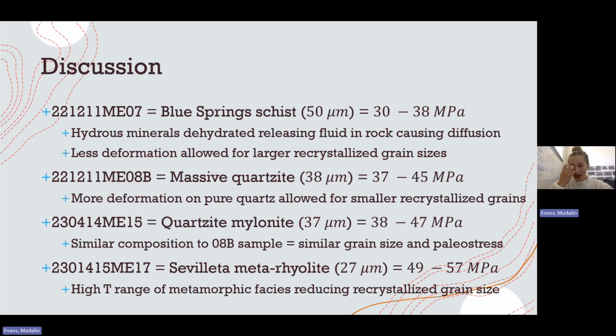Now, the quartzite mylonite initially derived within the massive quartzite unit, allowing it to have a similar composition, especially to this previous sample here, meaning that it is appropriate to have the same recrystallized grain size and paleostress as the 08B sample. The 17 sample was located in the Sevilleta metarhyolite and had a mean recrystallized grain size of 27 microns. This had a flow stress between 49 to 57 megapascals. And the idea for this one is that it had experienced the highest temperature range of metamorphic facies, therefore reducing the recrystallized grain size.